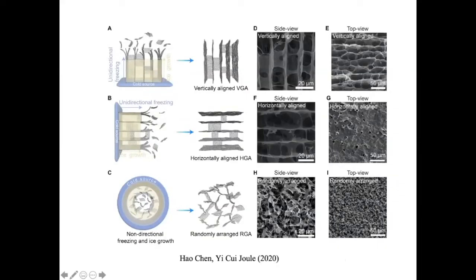So we have this hypothesis, and I started to work on this and develop a method using cooling, the ice crystal formation. This is graphene oxide dispersed in water, and then you cool down from the bottom, produce the ice, it crystallizes, and then it's going to propagate from bottom to the top. It turns out you can align graphene oxide vertically this way. So this produces a low tortuosity. You can also cool it down from the side and align graphene horizontally. Now you have a high tortuosity. We could also do surrounding cooling. Now you have a random distribution.